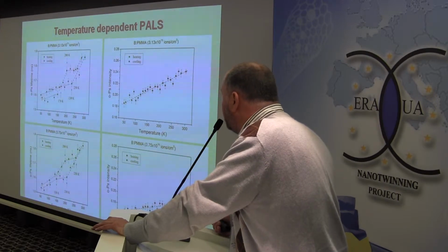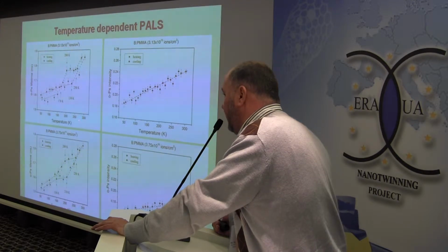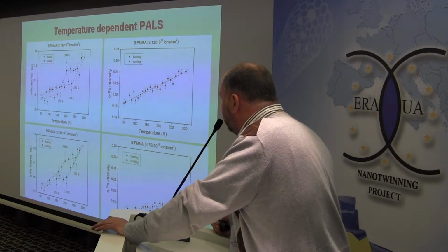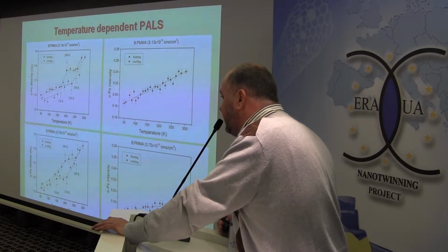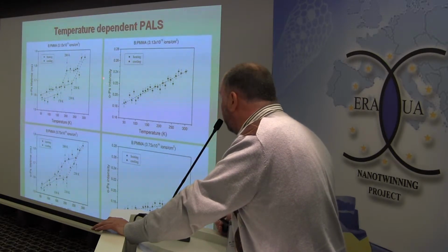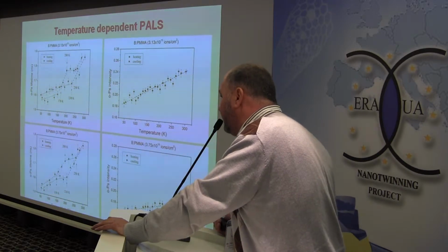According to the literature, the Tg for PMMA is more than 355 K. Between the gamma and beta transitions, the implanted sample shows something like a hysteresis curve, and the intensity is practically a linear function.